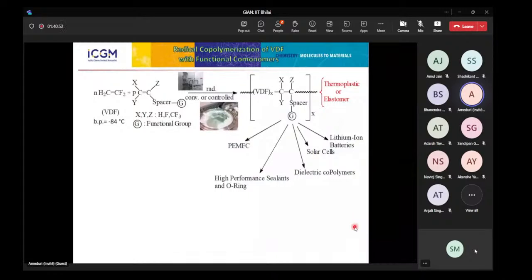So now the issue with PVDF is that there is no function. And indeed, if you really want to get some insight into the properties and the applications, it's necessary to have a function. So either you modify VDF or PVDF, or you directly find a suitable comonomer able to copolymerize with VDF. But keep in mind that you want, of course, to keep the backbone of VDF. So this means that you need a high amount of VDF.